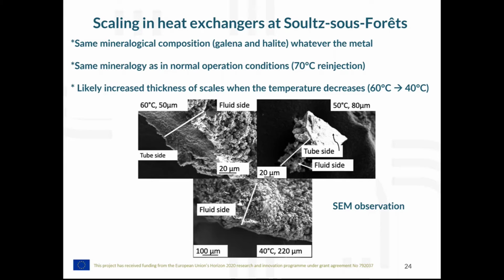And we tested the influence of the temperature on the thickness of the scales when the temperature decreases from 60 to 40 degrees. And we see that at 60 degrees, upper left corner, the thickness of the scale on a given metal is 50 micrometers. And you see on the top of this figure, the fluid side, which is rough, and the tube side, which is smooth. When the temperature decreases to 50 degrees centigrade, the thickness tends to increase up to 80 micrometers. And on the lower figure, we see the thickness has increased up to 220 micrometers at 40 degrees centigrade.